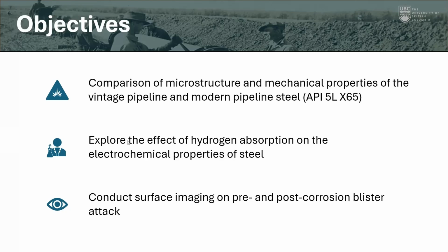And then we also looked at the effect of hydrogen absorption. So let's say this pipe was exposed to a sour gas. And then we would want to see how, based on the microstructure that we just previously assessed, that hydrogen is accumulated in those inclusion sites. And then when exposed to a new CO2 rich environment, so during that transition from old to new environment of CO2, how does this hydrogen surface damage behave or accelerate, let's say, corrosion of steel?